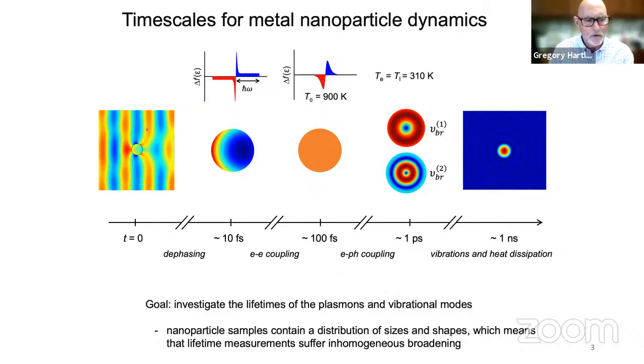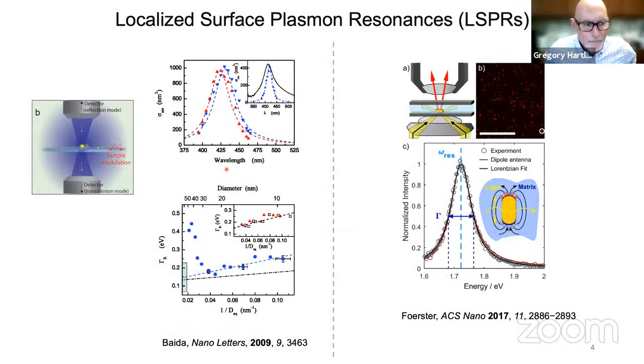Okay, so let's start off with discussing what happens to the dephasing of the plasmons. This is a very, very fast process, and it's really right at the edge or even beyond what you could measure just through ultrafast spectroscopy. So the way to get lifetime information when you look at the plasmons is to actually measure a spectrum of a single particle, and then the width of the spectrum will give you information about the lifetime. These are some example spectra taken by the Lyon group, Fabrice Vallée and his colleagues at Lyon, and also by Stefan and some of his colleagues. I think the experiments were done in Germany.